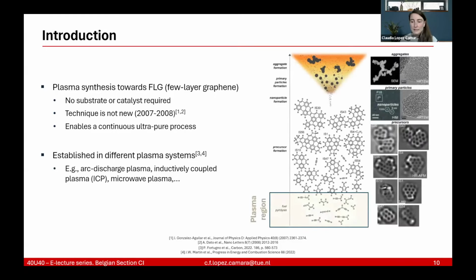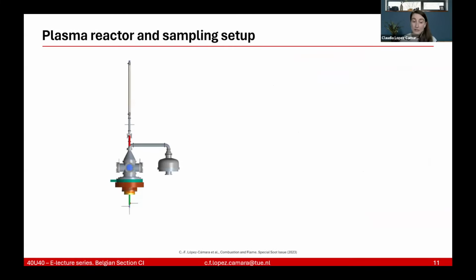And this is basically a schematic with pictures from TEM and AFM about the evolution that some previous people had reported in the literature. And basically the plasma region is the one that I highlighted here. With that, we were going to use the microwave plasma setup, in which we injected the reactor gas inlet from the bottom. So that's where the precursor was being injected. Then we had the microwave plasma resonator, which is the orange part there. Then we had the filter at the beginning.